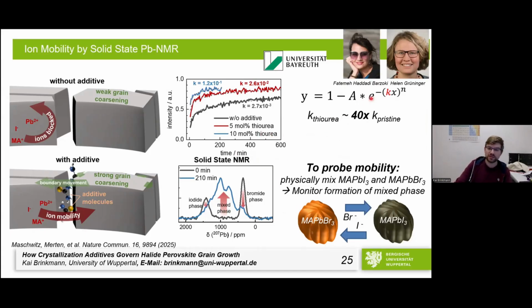And then we can basically put a fit to it, put a relatively straightforward diffusion equation here, and just use the fitting parameters to compare how fast this mixing occurs. And interestingly, for thiourea, we ended up with roughly 40 times what we call the mobility parameter, or it's just a fitting parameter K that we need in order to model the mixing with thiourea than without.